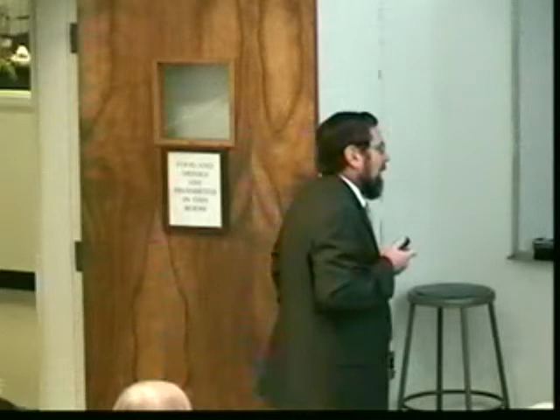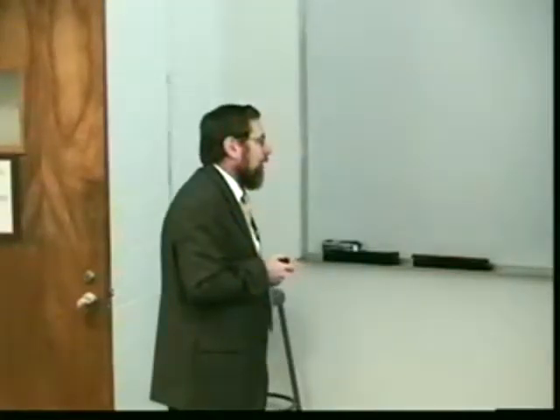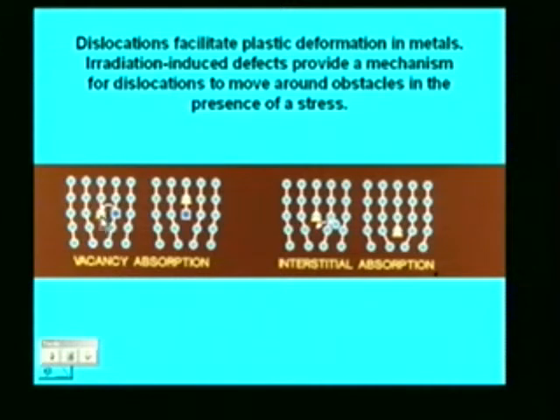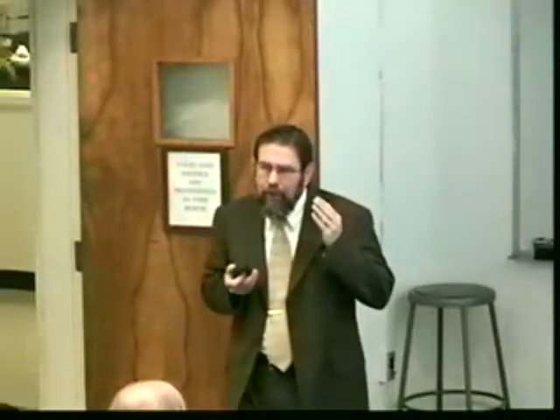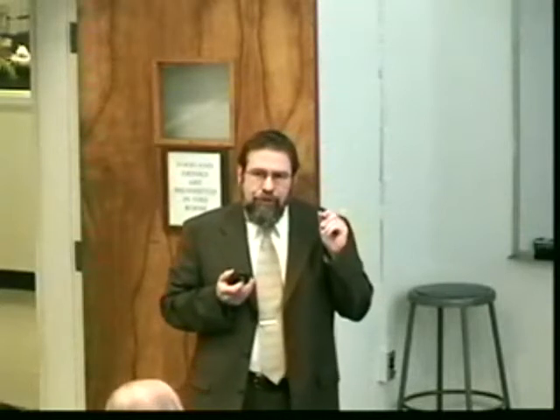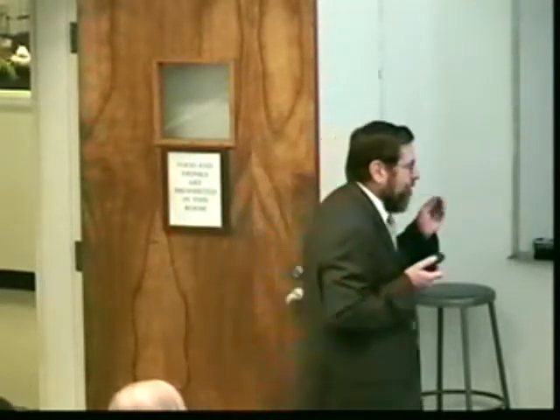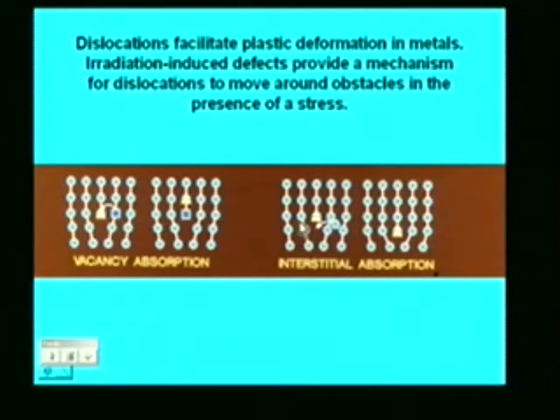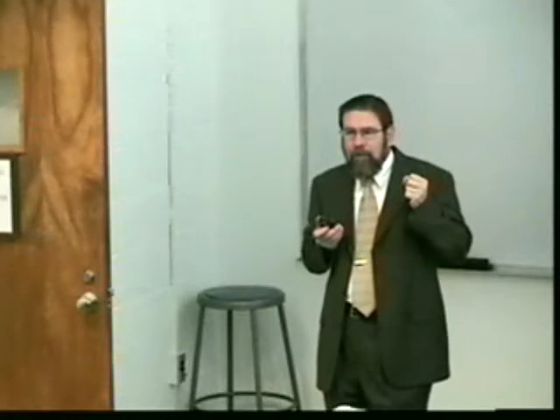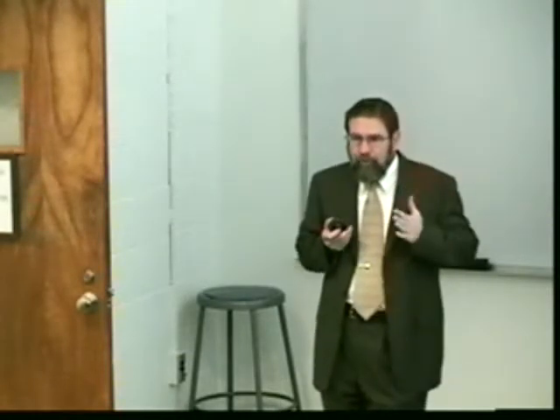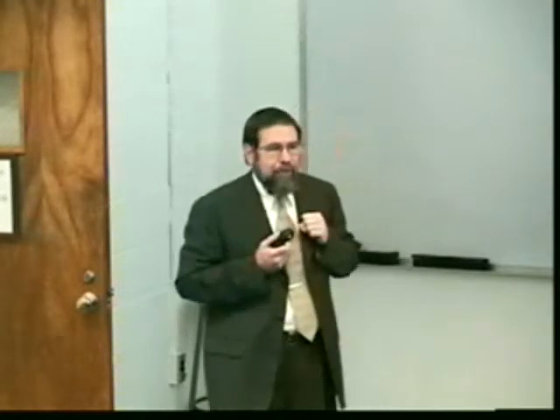Now, if we were to have a vacancy go to the edge of that row of atoms, then effectively that row of atoms would move up one lattice constant. Or if an interstitial diffused into that site, that row would move down. So dislocations can climb, up and down, by diffusing interstitials and vacancies. So they can move. And if the dislocation is tied to a defect by an elastic stress, then these defects can cause it to move around these objects and enhance plastic deformation.